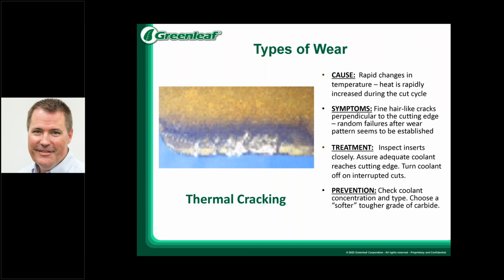As the cracks form, this does allow for the material to actually get pushed into it during the high heat of a cutting operation. This is sometimes mistaken for chipping, so that's where running in shorter intervals, taking a chance to pull out the inserts and look at them, whether under a microscope or with a loupe, you can help determine what the type of wear is and what changes you may need to alter in your process.